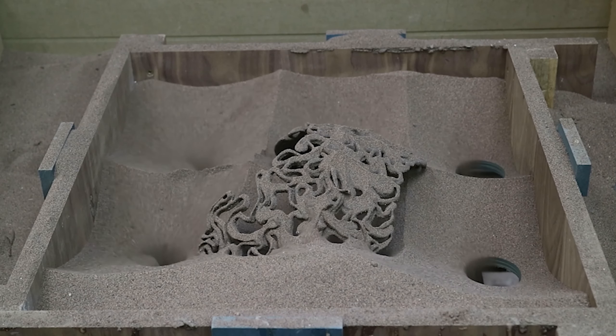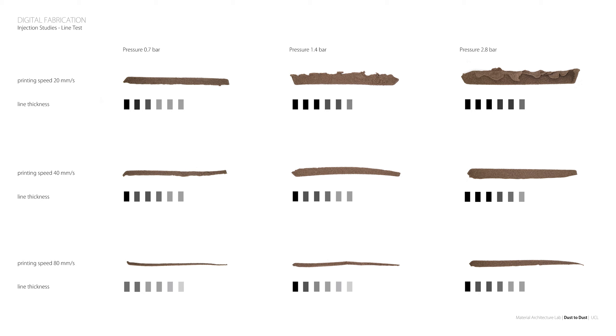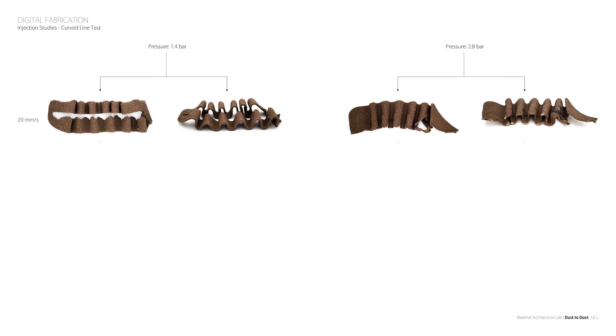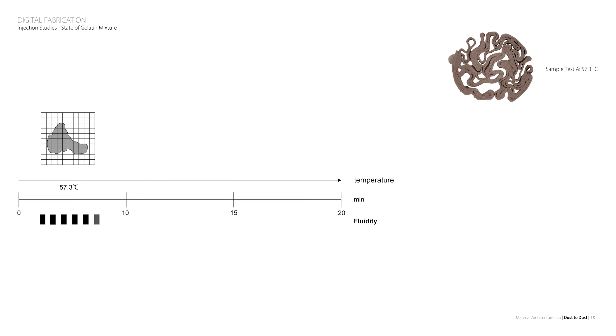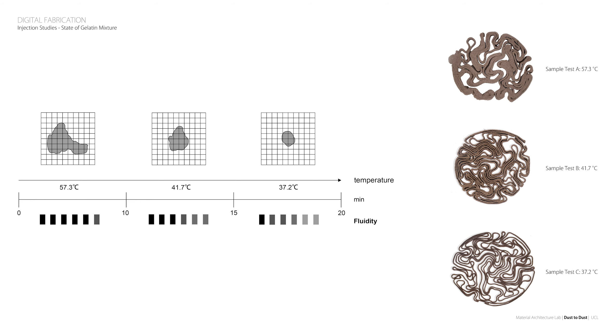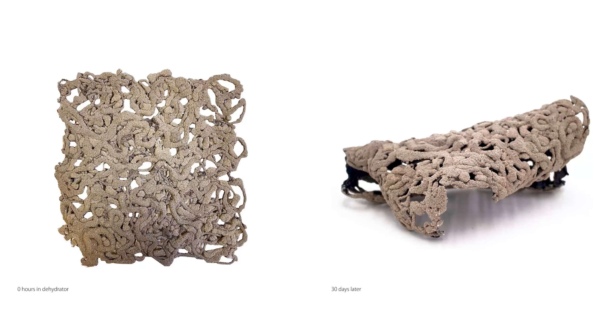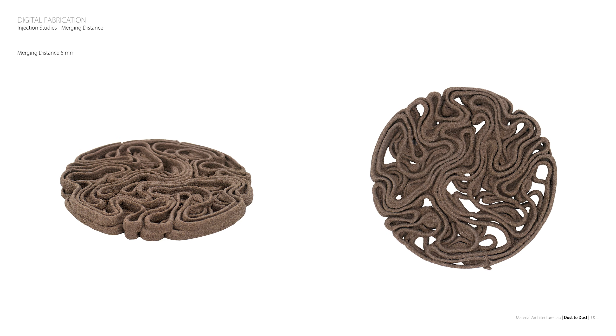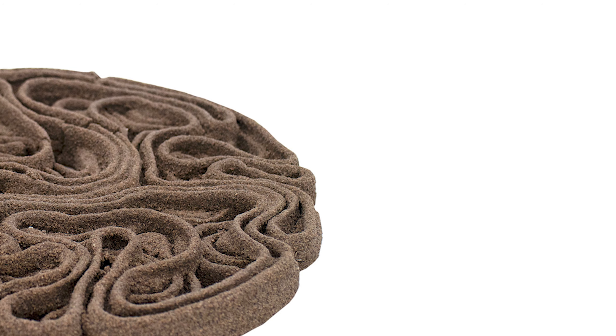Once the binder is fully cured, we remove the aggregates. We use sand as the aggregate while the binder dries. The robotic arm is used to deliver the gelatin binder. We precisely control the geometry, size and thickness of the structure by adjusting the movement, position and speed of the robot arm. We wanted a product with controlled processes and defined outcomes. Whilst maintaining control and predictability, we also allowed for the free bleeding of material in the sand and the natural shrinkage of the model after drying. The research illustrated that it was practically impossible to print two perfectly comparable objects. With this conclusion, we used the unpredictable nature of the material to drive the design of the following structures, which challenges conventional design parameters.